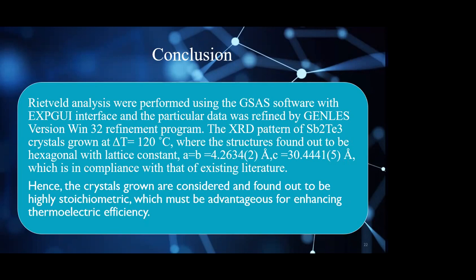In summary, the XRD pattern of Sb2Te3 crystals grown at 120 degrees Celsius, where the structures were found to be hexagonal with the lattice constant a equals b equals 4.2634 angstrom, c is 30.4441 angstrom, which is in compliance with that of existing literature. Hence, the crystals grown are found to be highly stoichiometric, which must be advantageous for enhancing thermoelectric efficiency.